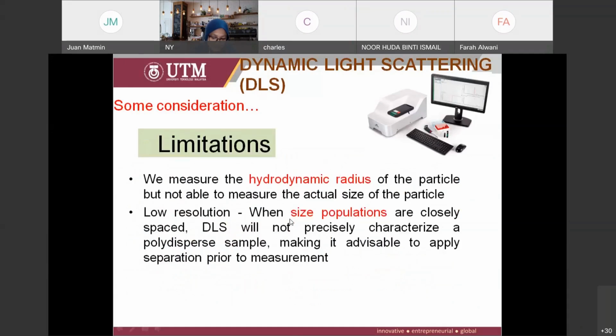Okay, and take note, as mentioned earlier, DLS has the limitation of a true particle size. It's only giving you the measurement of the hydrodynamic radius, and you're also going to get a low resolution of sample, provided that the sample here is closely populated, meaning that a highly aggregated sample will not give you a precise measurement. That's why in our result earlier, we found that the distribution of sample is around 800, but when we look at details based on the TEM, it's actually around 500 nanometers only. So that is why we always have to counter-check and confirm our measurement.